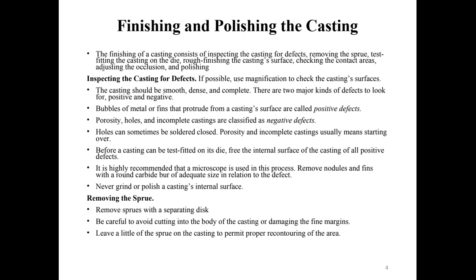In terms of the holes and the soldering process, it's true that they can be soldered, but the size of the holes also counts. If the holes are too big to be soldered, it's not recommended. It's recommended to start all over again. Why? Because even though the solder metal is compatible with the metal of the casting, the bond between the two of them is not always 100%. Also, the solder sometimes doesn't have the same ceramic bonding ability with porcelain as the metal that we use for the coping. So that's very important. If there is a small hole, maybe we can solder, but if there is a big hole, it's recommended to redo the coping.